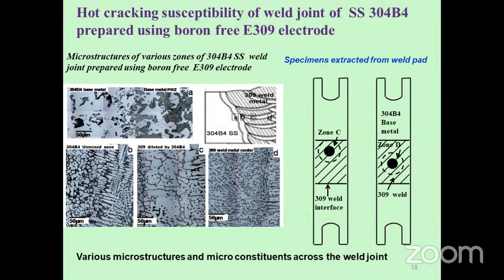Now coming to the scenario where we are welding this borated stainless steel using a boron-free consumable, that is 309 weld metal, which does not have boron. Here we see the microstructure of the weld joined using 309 weld metal without any boron. This is the borated stainless steel base metal having micron-sized borides in the matrix, and this is the partially melted zone where these borides are melted but the austenite matrix is intact. And we have another zone called the unmixed zone because of the variation in melting point between the welding consumable and the base metal.